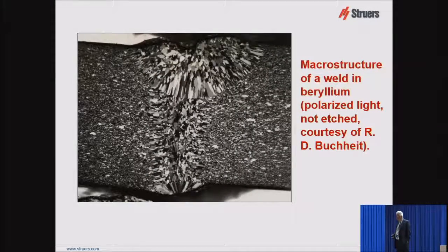Now, here is a sample of beryllium. This is a weld in beryllium. You can see a weld nugget up here, and there's a smaller one down here, and a fusion line down the middle, and this is base metal out here. This was polished and taken as polished in polarized light, but without any color